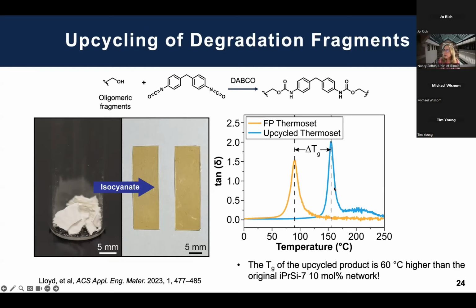The upcycled material that comes from these oligomeric fragments that we recovered actually has a higher glass transition temperature. It's really quite a good material that we've made. And the strategy as we move forward has been to start adding these fragments into pure monomer, just like you do with recycled polymers. I haven't put the data in this talk, but we can put 30% of the recovered oligomers into monomer and get a pretty good polymer out.